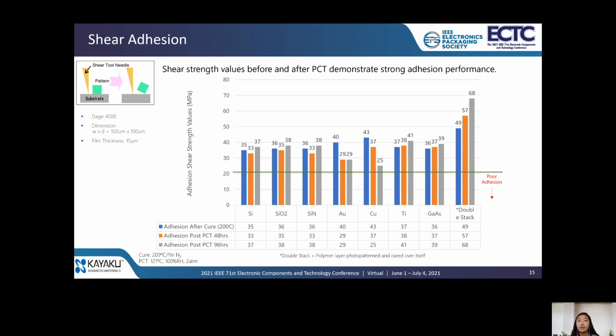I do want to note that the significant drop in copper adhesion after 96 hours is probably due to the copper substrate just oxidizing itself. When we tested the PRL-29 on copper using the crosshatch tape peel test after PCT, the material did pass. So I think that's what this is showing.